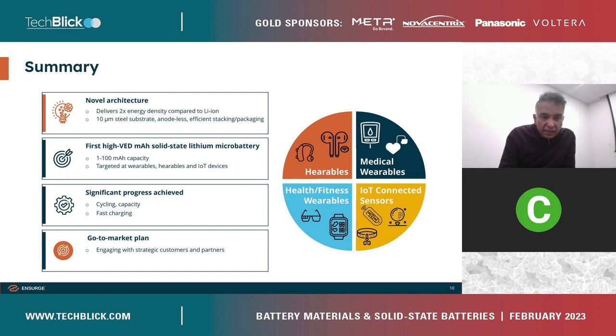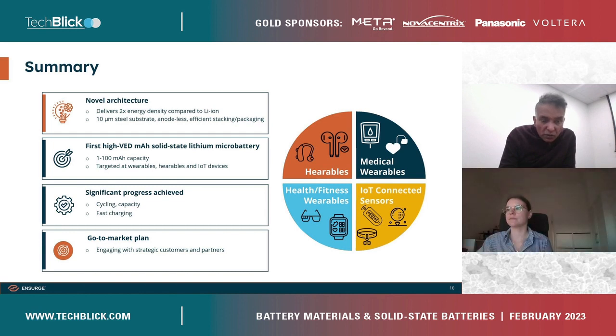In summary, the key take-home points. What we have is a novel architecture which has been simplified and adapted to roll manufacturing on stainless steel to get to very high energy densities. Our targeted energy densities are in the range of about 700 watt hours a liter, which in the small form factor, for example in the range of about 10 to 16 milliampere hour or 50 milliampere hour, is probably twice what you would get from an equivalent lithium ion cell.